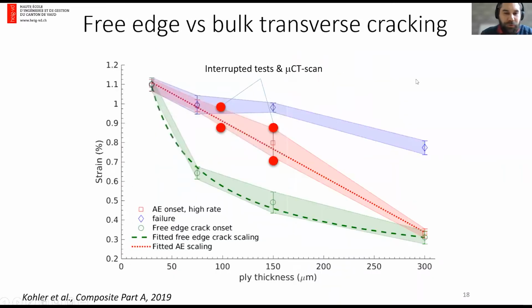If we look closer to what happens, if we look at the free edge, we can see that at the free edge, the onset of damage is not exactly the same. So the onset of free edge cracking does not correspond to the onset of acoustic emission. Actually, the first free edge cracks appear earlier than the onset of acoustic emission.